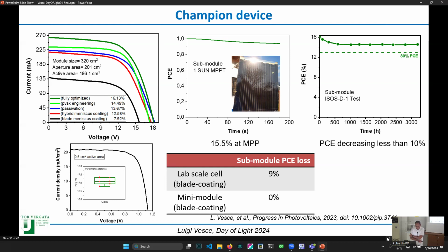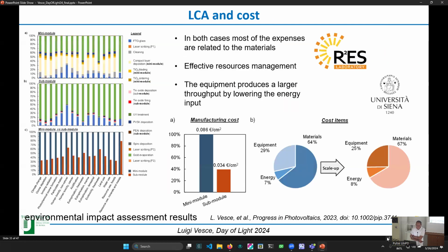Here is the stabilized efficiency of 15.5% with a short light soaking, and also the stability according to the ISOS-D1 test. ISOS-D1 is a shelf life test. So we are not applying temperature or light. We are just keeping the substrate in a drawer somewhere in the ambient environment. And here we have some decrease, about 10% after 3,000 hours.